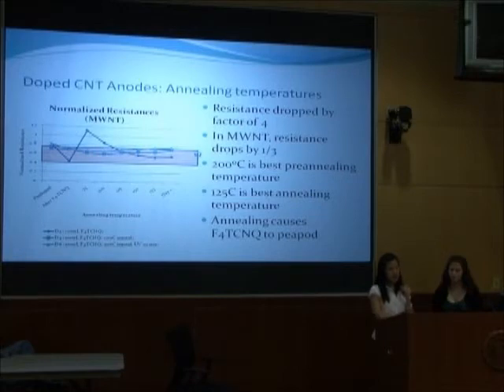We discovered that 200 degrees Celsius is the best pre-annealing temperature for the nanotube before doping, and 125 degrees Celsius the best post-doping annealing temperature. We predict this is the reason why, because annealing, first of all, helps the F4TCNQ to p-dope and intercalate into the nanotubes, and also because annealing causes impurities such as water and oxygen to evaporate.